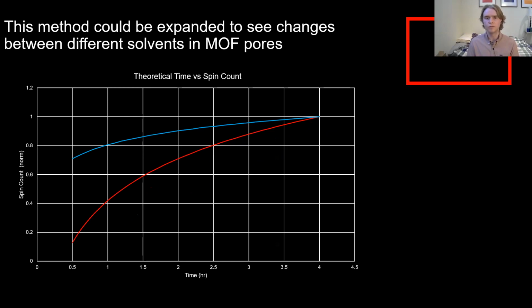So in the case of MOF5, it's already known that DMF is much harder to remove from the pores of MOF5 than chloroform is. Normally, if you want to use MOF5 for something, you will soak your synthesized MOF5 in chloroform for a while to remove all the DMF from the pores. But if we were able to see other aspects of guest inclusion using this technique, we could maybe see that the DMF would be something like the red curve, whereas the chloroform would be something like the blue curve, where chloroform is easier to remove, thus giving us a higher spin count earlier on.